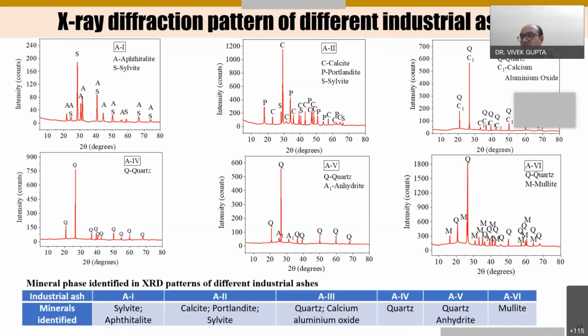Whenever we have a temperature of more than 1200 degrees Celsius in the thermal power plant, we generally find the presence of these mullite phases, and it reduces the reactivity. So you will see that although we are getting low LOI in the A6, still we are not getting good lime reactivity when we see the results of the macro test.